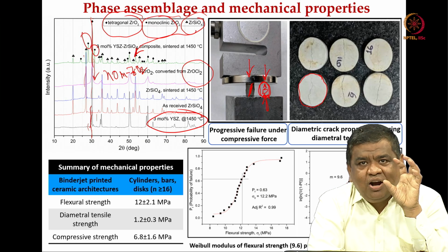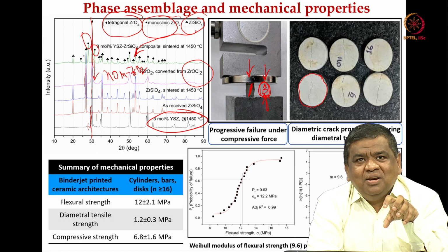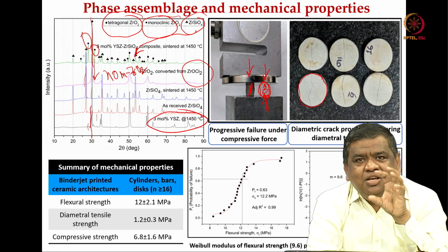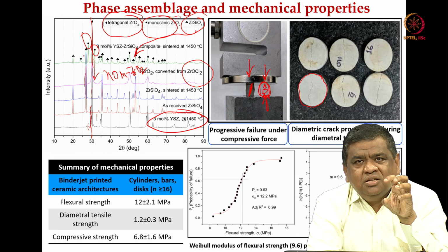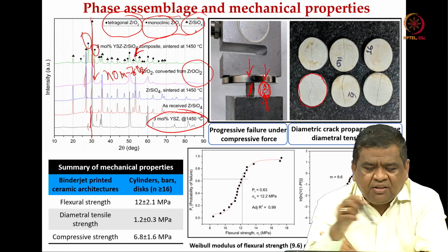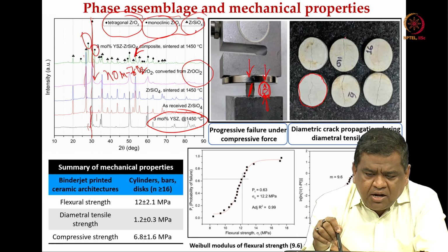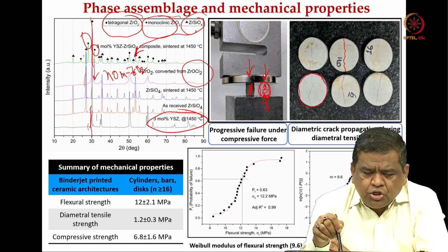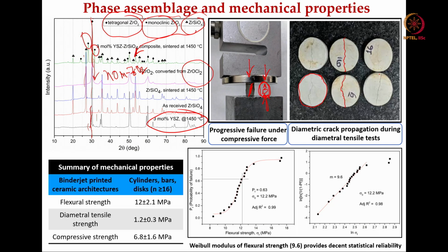So, this is one of the ways for ceramic materials one can measure tensile strength, because you take the diametral compression samples, put them under compression, and essentially measure the tensile strength. And the reliability of the test results has to be validated by showing observations or evidences where you can clearly see the cracks propagate along the diameter.